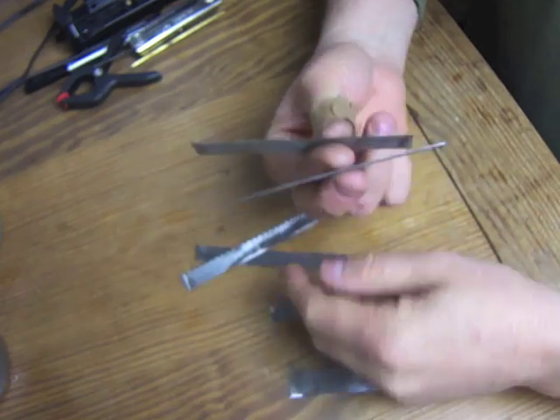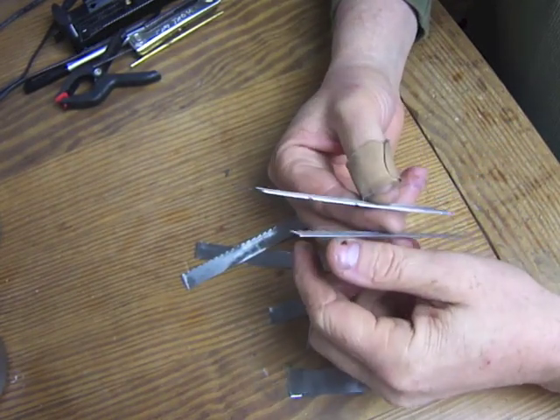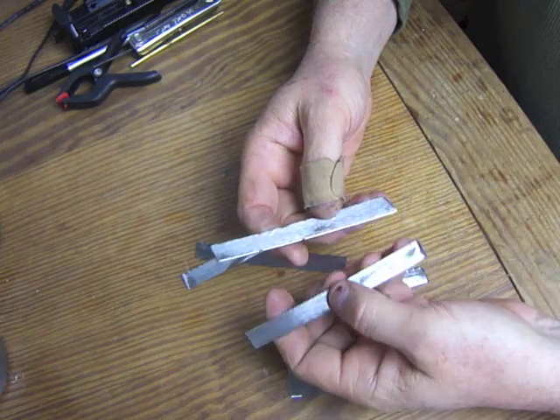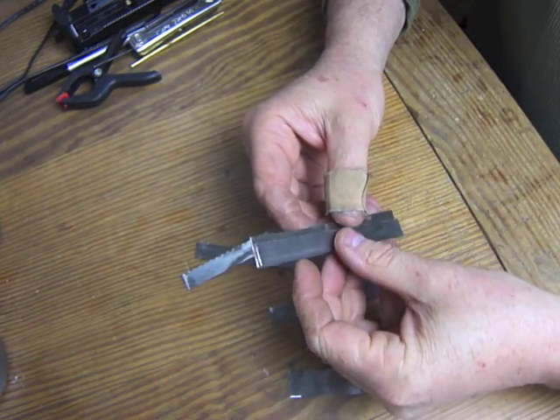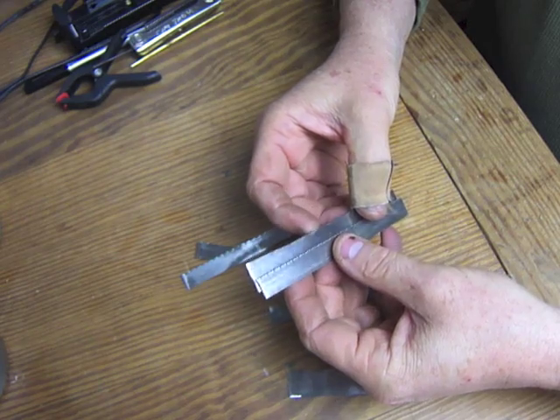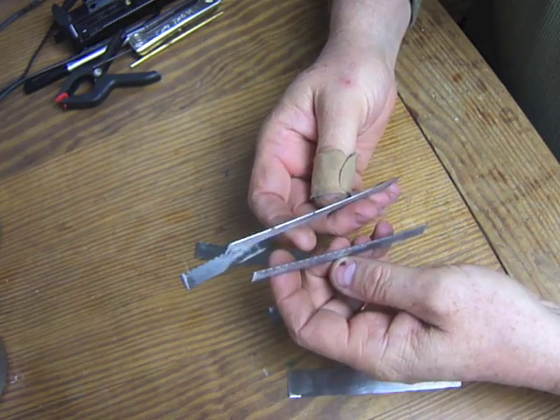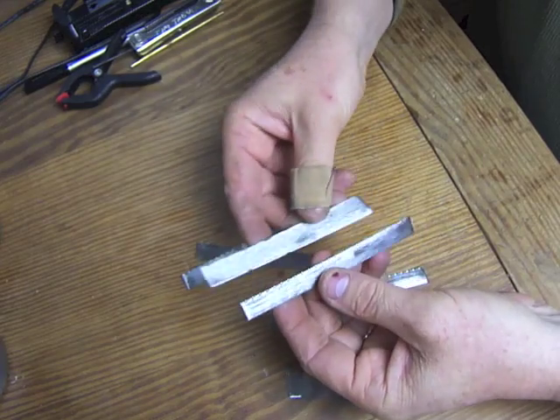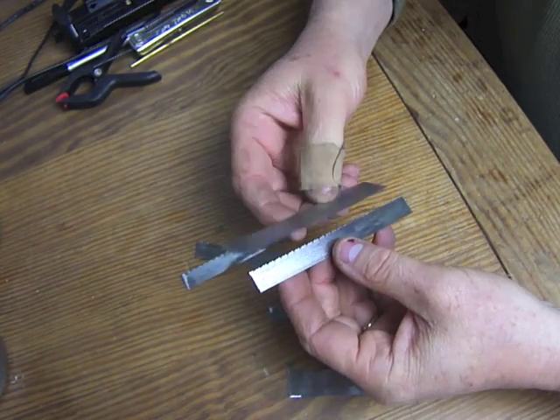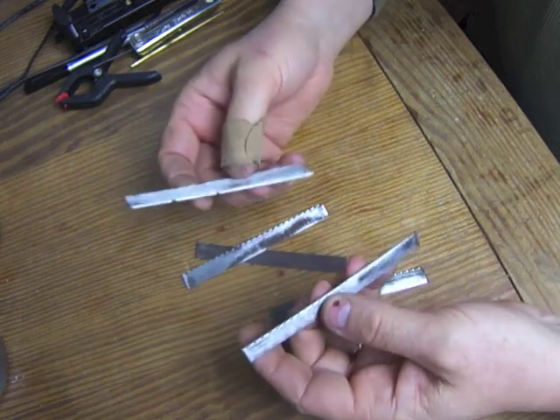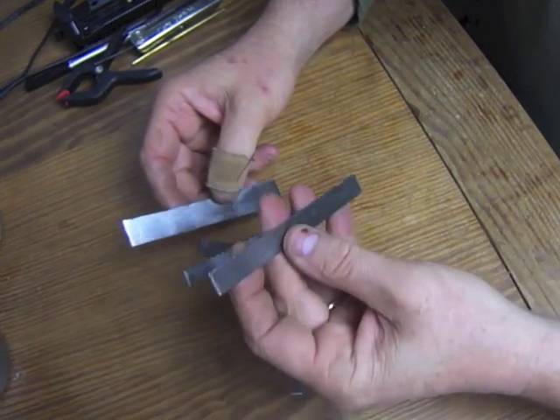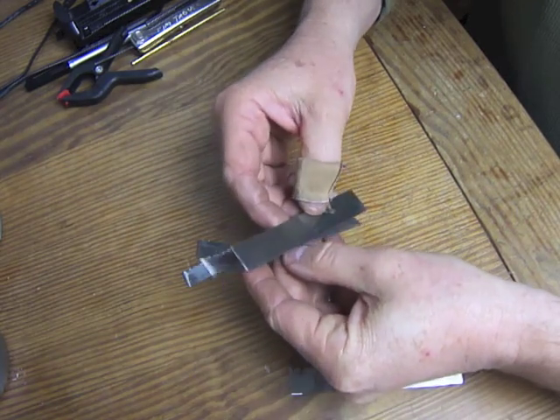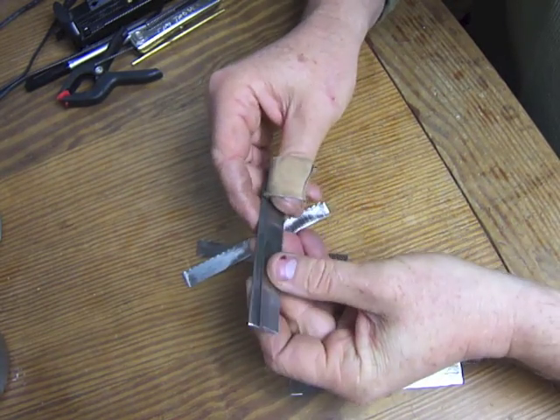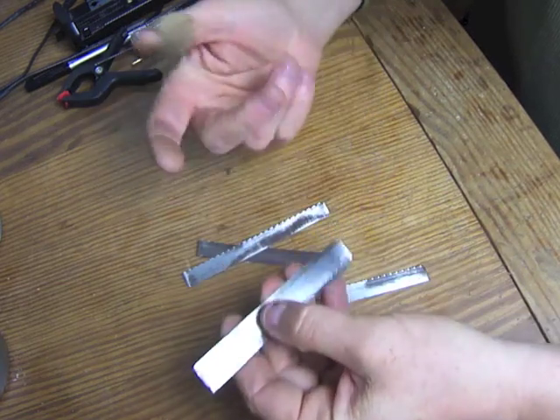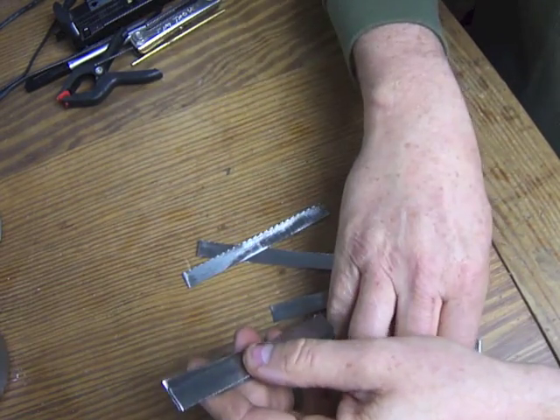And as you can see, this stock is really thin, so the only consideration we have for this is making sure that it's really flat together when we're making the Damascus, and that it's easier to burn the outer layers of the steel when we're using thin stock like this. But this is going to give us our contrast, and again, ideally these should be exactly the same size, but this is just a down and dirty demonstration here.